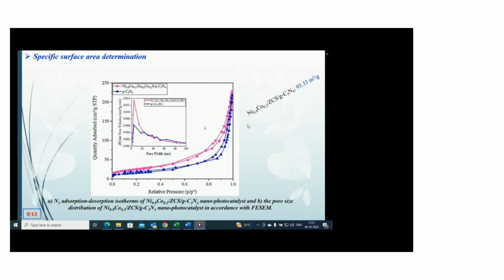And according to the figure, the hysteresis loop shape in both isotherms is type H3, which is indicative of plate-like particles with slit-shaped pores. And according to the inset, the pore size distribution curves reveal a broad range of pore sizes ranging from 2 to 100 nanometers, with the prominent peak centered at 4.6 nanometers. This further confirmed the presence of a mesoporous structure.